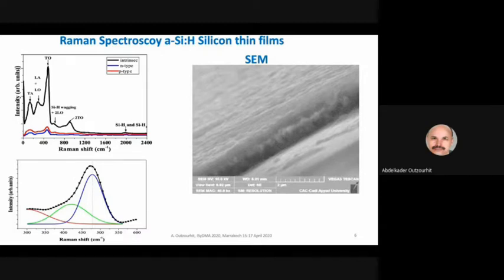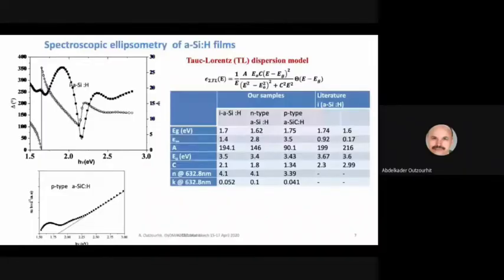or enhances it rather. Okay, so we also did some ellipsometric measurements on the films in order to determine their optical properties, mainly the optical band gap, the thickness, in addition to the refractive index, and so on. So this figure shows the ellipsometric parameters, the phase angle, and also the amplitude parameter as a function of the photon energy. The experimental results are indicated by points, and the fits that were obtained using the widely used Tauc-Lorentz dispersion model are also presented in this figure. This is the line here. And as you can see, the fitting results in very good agreement with the experimental results,